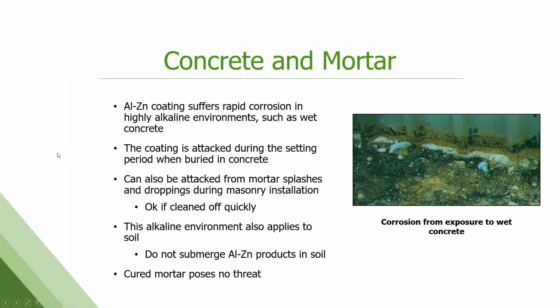Concrete and mortar. Again, aluminum. The aluminum component in this product suffers from rapid corrosion when in contact with wet concrete. So you want to make sure there's always a barrier there to protect it from having direct contact. It can also be attacked from mortar splashes and droppings during masonry work.